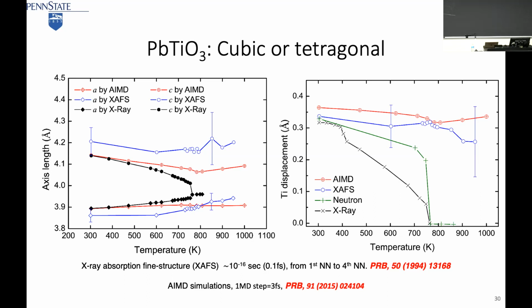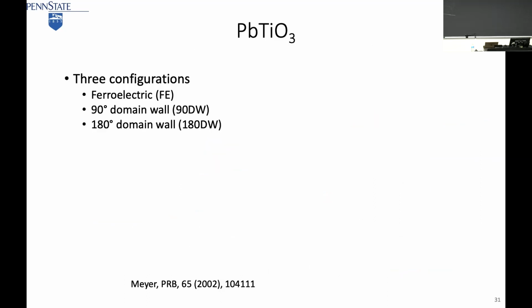As we see next, we have to figure out what configurations we have. So you think about if at 0 Kelvin, all the polarization lines up, you get one ferroelectric configuration. Okay. And when one goes to this one, you get a 90 degree domain. If the titanium goes in the opposite direction, you get a 180 degree domain. There are only 3 configurations possible. First the ferroelectric, the second one is the 90 degree domain, and the 180 degree. Only 3 configurations from this complex structure.